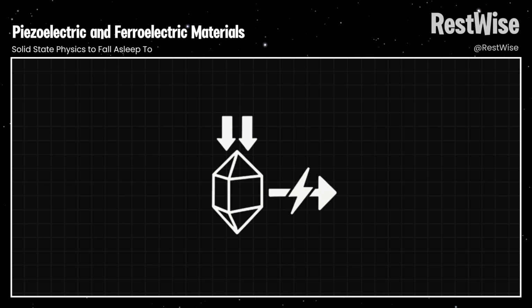To sum it all up, piezoelectric materials generate voltage from mechanical stress and deform when you apply voltage. Ferroelectric materials take that further, offering permanent polarization and reversible switching, with hysteresis and memory-like behavior. They both rely on non-centrosymmetric crystal structures, internal dipoles, and domain physics to do their magic, and their impact on modern tech is massive.